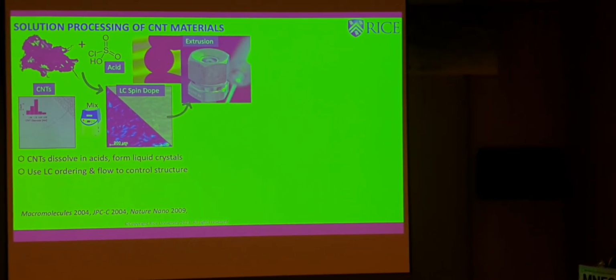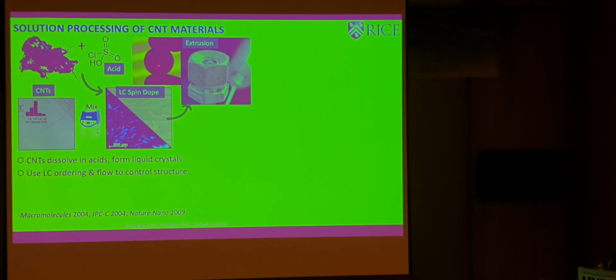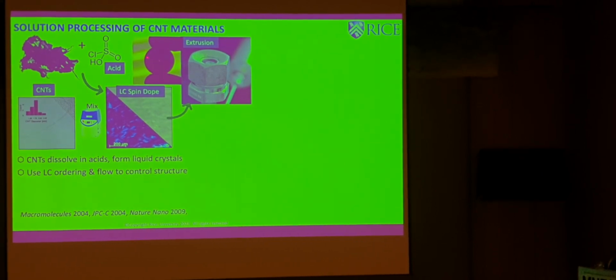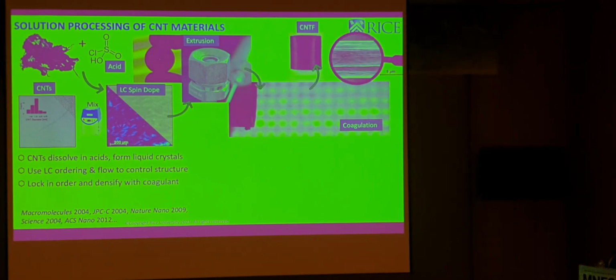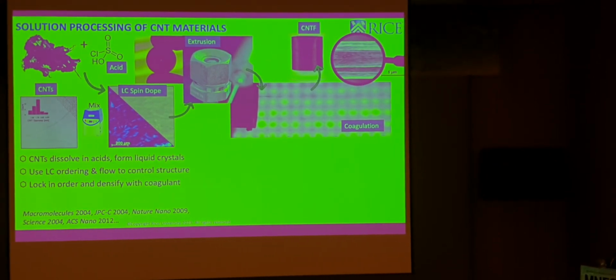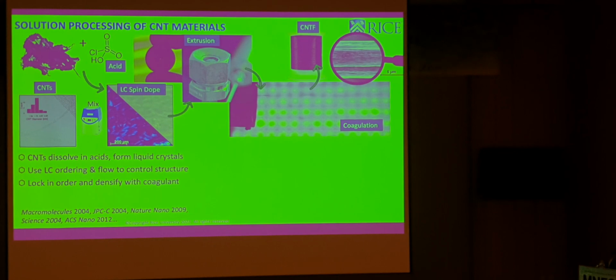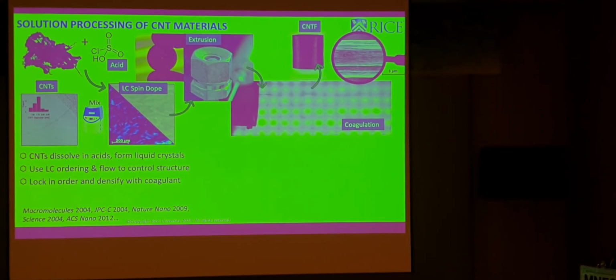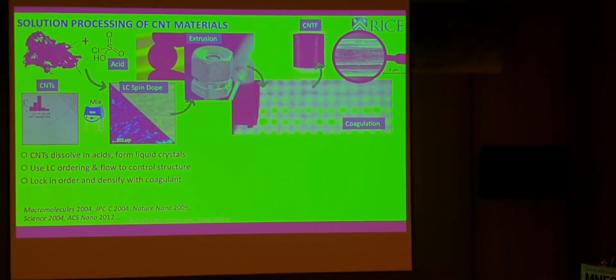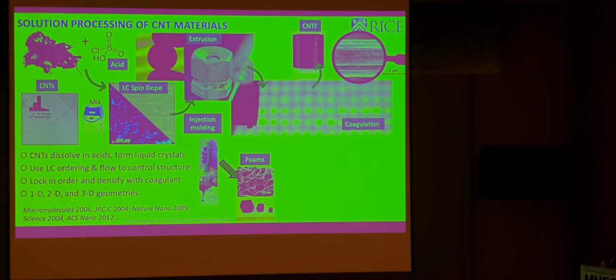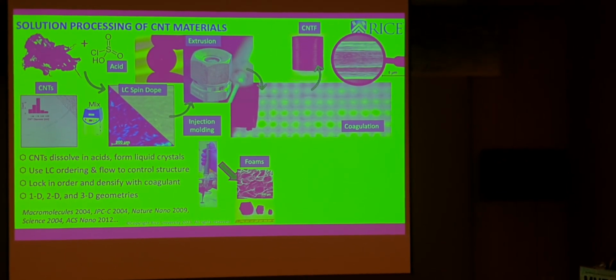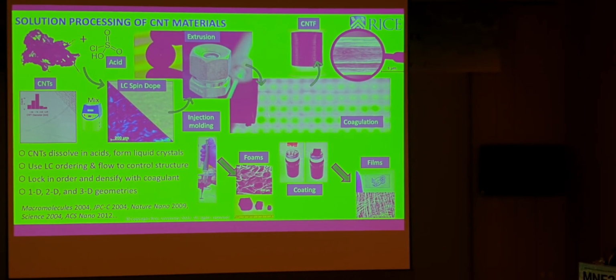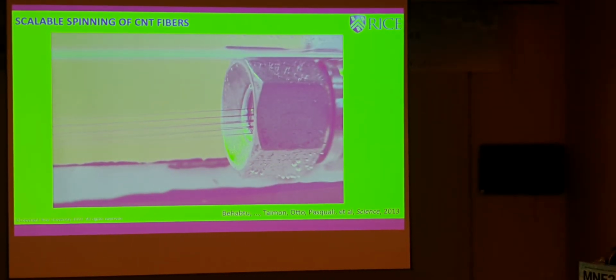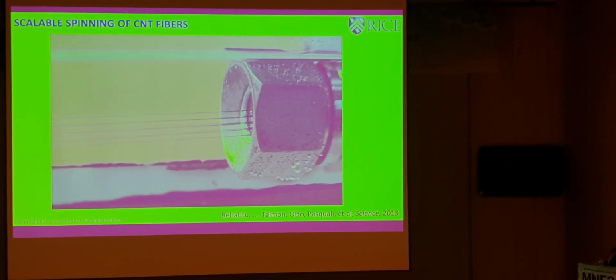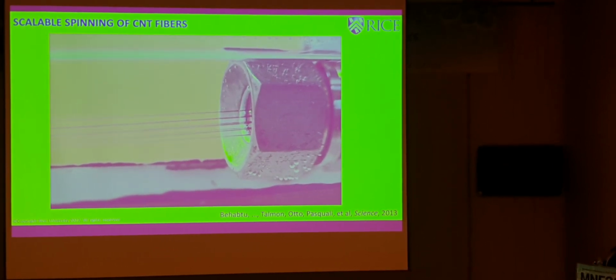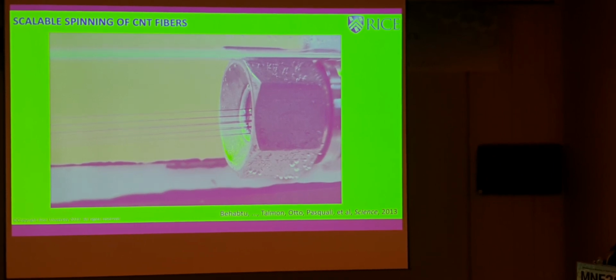And then you can use the liquid crystal ordering to control the liquid, and then spin out of a spinneret. That's a spinneret over here that has only one hole. And spin into a coagulant, remove the acid, and pick up the fiber. And you get naturally this very well aligned fiber because the nanotubes are already aligned in the liquid. You can also make foams by injection molding, and you can make films or coatings, and then you can see that this is scalable, right? So this is now with a multi-filament spinneret. So that's where we were in 2013.